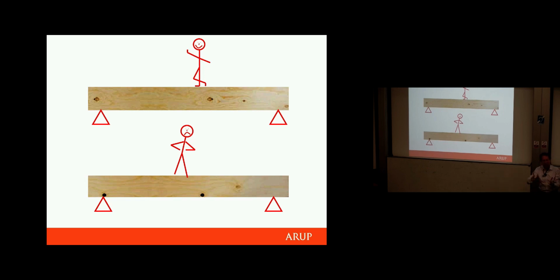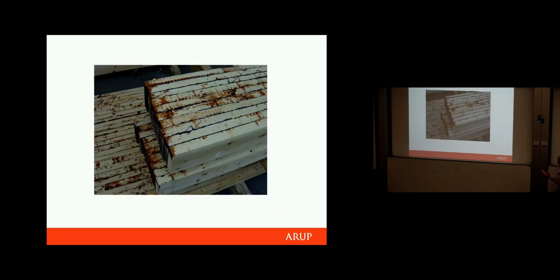Take the trunk, chop it up into pieces, glue them all randomly together. Those knots, those holes, don't go all the way through. And so we just know from testing, we end up with something stronger. And basically, the thinner you make your planks or your laminates, the stronger it becomes, because the impact of any one knot in any one layer becomes less and less. So glulam is perhaps 30% stronger than the parent wood. And if you went to laminated veneer lumber, where your laminates are only 3mm thick, then that can be 50–60% stronger than the parent wood that you started with.